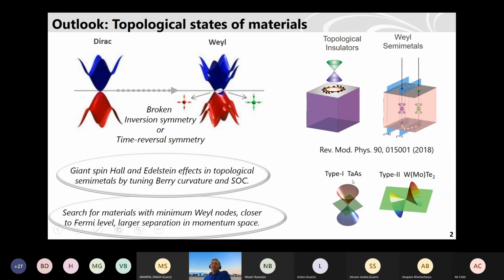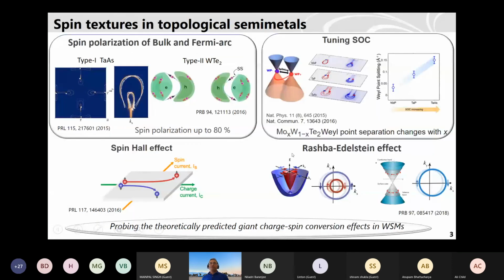Also, in some materials, like type 1 topological Weyl semimetals such as tantalum arsenide, you have these Weyl nodes. In type 2, it's actually tilted, and that will be interesting to see. The number of Weyl nodes in the system is large; some have more than 8, multiple Weyl nodes. So what people are looking for is a material with a minimum number of Weyl nodes, closer to the Fermi level, and with large separation between Weyl nodes in momentum space. This separation between the Weyl nodes should be large so that it can be more tunable. Such examples also exist.